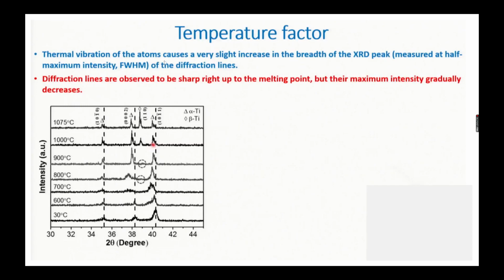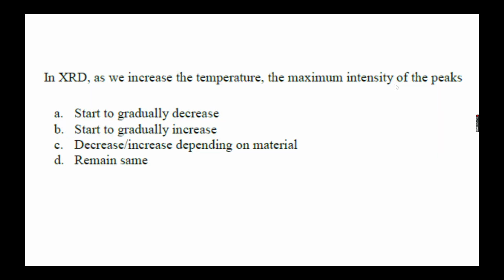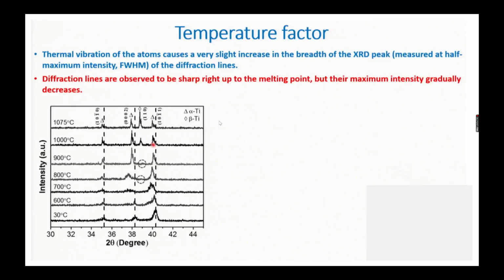Here the thermal vibration of the atoms causes a very slight increase in the breadth of the XRD peak, and the diffraction lines are observed to be sharp right up to the melting point, but their maximum intensity gradually decreases. So whatever the maximum intensity is, it will decrease when you raise the temperature. As you can see in this peak, at 30 degrees centigrade the peak intensity is higher. When you go to higher and higher temperature, the peak intensity at 1075 degrees is much lower than at 30 degrees. So the maximum intensity of a peak gradually decreases with increasing temperature. You can find this in variable-temperature XRD data.